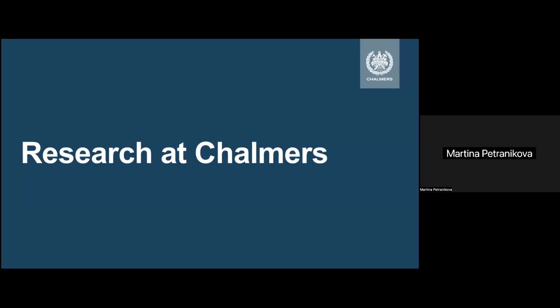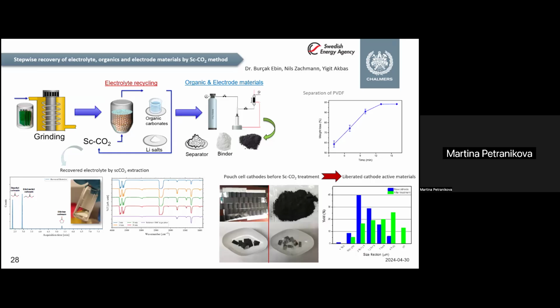So what we do at Chalmers. Since I'm supposed to talk about the hydrometallurgical processing, I wanted to just mention shortly that we are also focusing on the removal of the electrolyte, and we are using supercritical CO2 for that. A colleague of mine, Dr. Burçak Ebin, and his PhD students, are using supercritical CO2, where they can very effectively remove the electrolyte and then also the binder, which helps us in the hydrometallurgical processing to get more pure material. So if you're interested in their results, they have published several papers, and you can also contact them.